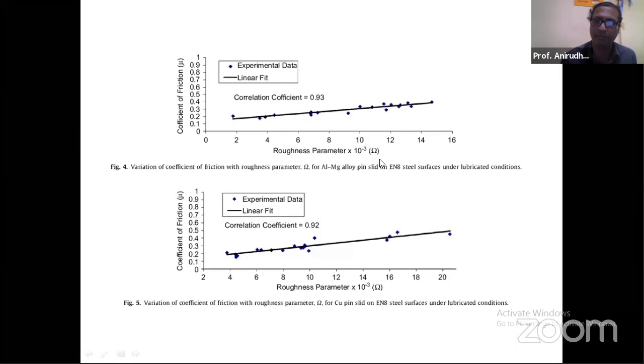Mind you, this is a very novel parameter. Nobody had done this before. I shouldn't say this, this is not an advertisement for what I have done, but still, this idea was new. This parameter is also new. Then when we plotted these experimental values of friction against that parameter that we formulated, we see that it's almost falling in line, with a correlation coefficient of 0.93 for this experiment, which means this descriptive hybrid parameter of the surface is largely able to explain the changes in friction for these different surfaces.